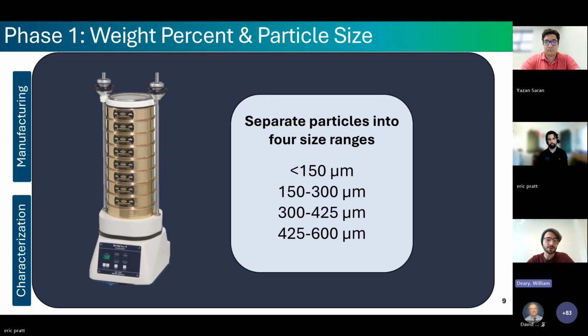This sieving step was also essential because without controlling our particle size directly, we wouldn't have been able to isolate its effect on the blend performance later on in the study. And it also reflects a practical reality of working with any reclaimed material, since unlike virgin materials, the jet milled cross-linked polyethylene arrived with a very broad and inconsistent size distribution. So we needed to get a repeatable starting point for the rest of our matrix.